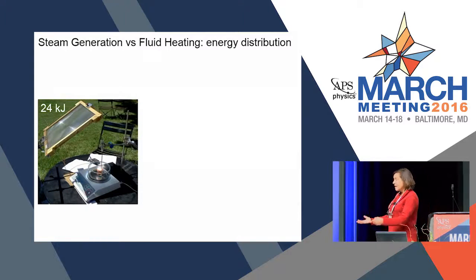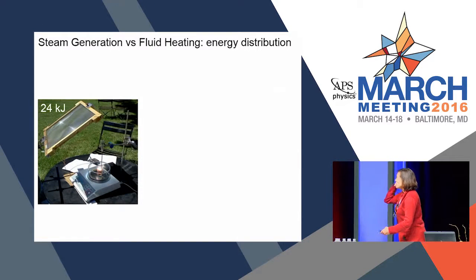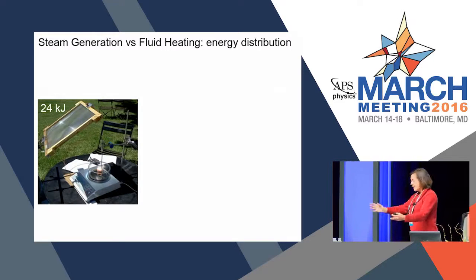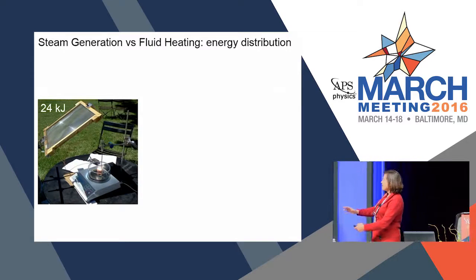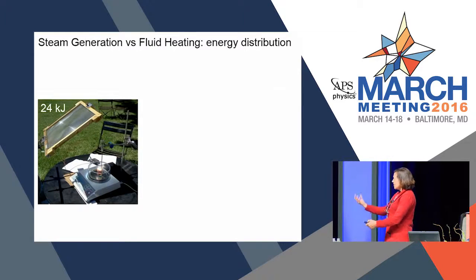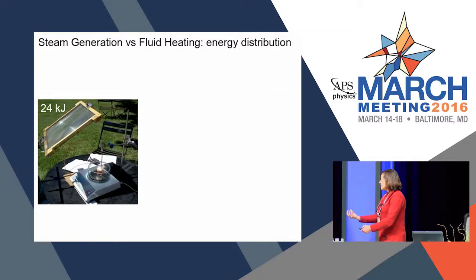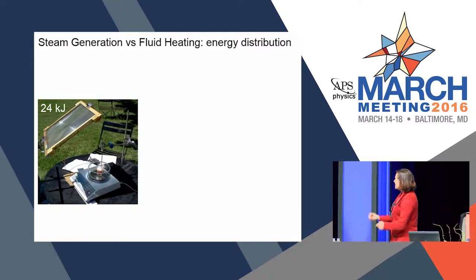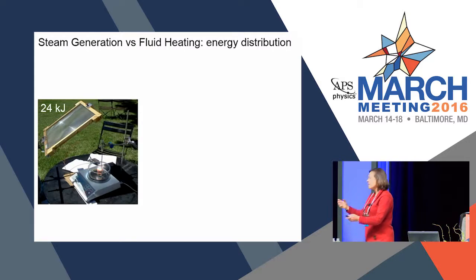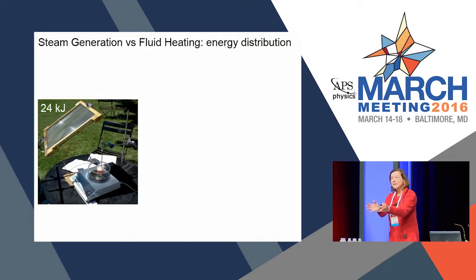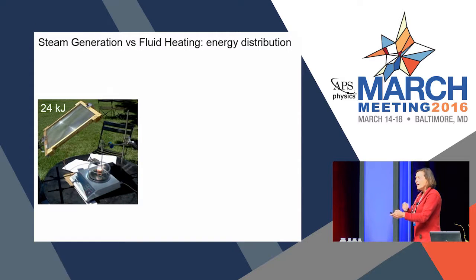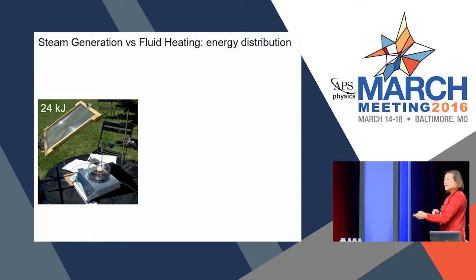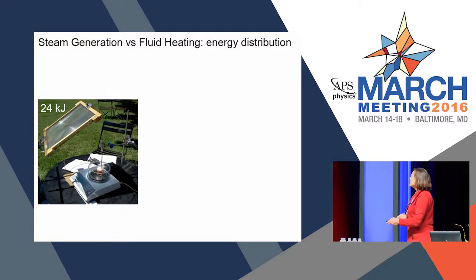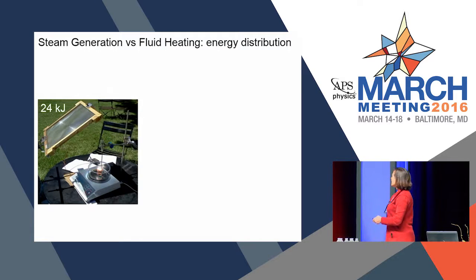So we can look at the energy distribution. We can do the experiment again, and again we're working outside. Our solar simulator is really the sun. So we take a solution of nanoparticles, and we focus sunlight on the solution. We have a thermocouple, but then we also put the whole thing on an analytical balance. So that way, the mass loss is the steam generation. So we can measure both the temperature increase of the fluid and the steam generation rate simultaneously.